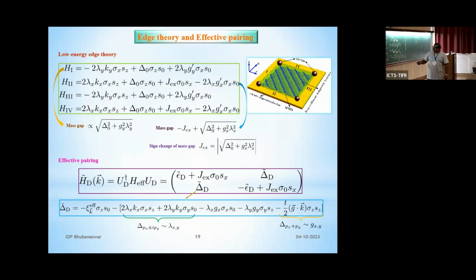Now, if the mass gap here is completely positive, but I can make the mass gap along edge 2 negative, then I know that this positive and negative mass, according to the Jackiw-Rebbi theorem, will give me a zero mode at the corner. So from the bulk and also from the edge, because the second order topology definition is that your bulk is gapped and the edge is also gapped. The bulk you have to characterize by this quadrupole moment, where the bulk band inversion will be there, and also at the edges, you have different mass sign change. For that reason, you can have the appearance of the Majorana mode. So both bulk and edge one has to see.